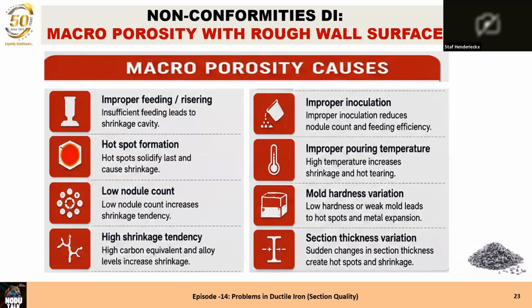The mold hardness variation, we have seen it in previous sessions already. There is an expansion in ductile iron during solidification. When the mold is not strong enough, not hard enough, that expansion will push out the mold, and that extra volume can lead to porosity, microporosity appearance. Then the section thickness variation: when we go from a thick section to a thin section and again to a thick section, that will block the feeding capacity of the risers, and if the feeding capacity of the risers is blocked, we can have this microporosity without any problem.